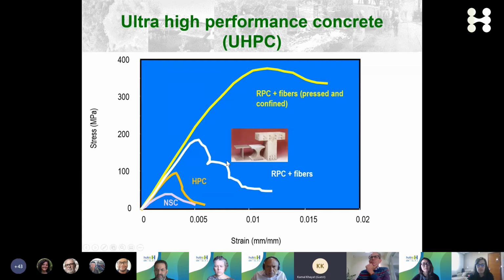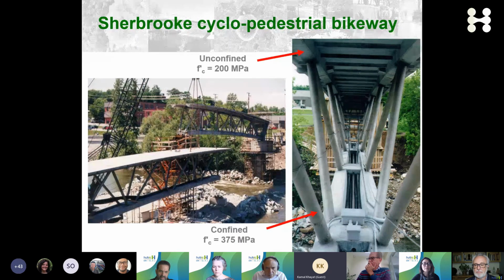And the record of high-strength concrete was shattered in the late 1990s by the introduction of, at the time, what was considered reactive powder concrete, now that we call ultra-high performance concrete, that can develop a compressive strength of 200 megapascal. And if confined, it can develop a compressive strength of 375 megapascal, which is the same structural capacity of steel. So by using UHPC, you can produce sections that are a lot more thin and a lot less wastage of materials.